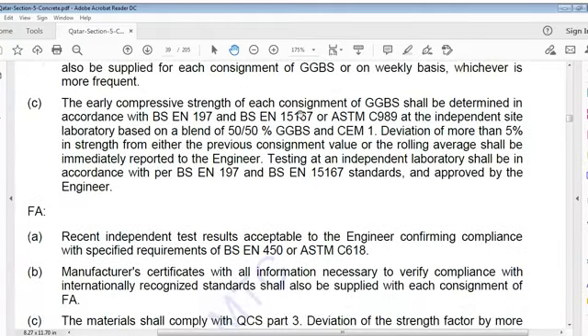Early compressive strength of each consignment of GGBS shall be determined in accordance with BS EN 197 and BS EN 15167 or ASTM C989 at independent site laboratory based on a blend of 50/50% GGBS and CEM I. Deviation of more than 5% in strength from either previous consignment value or rolling average shall be immediately reported to engineer. Testing at an independent laboratory shall be in accordance with BS EN 197 and BS EN 15167 standard and approved by engineer.